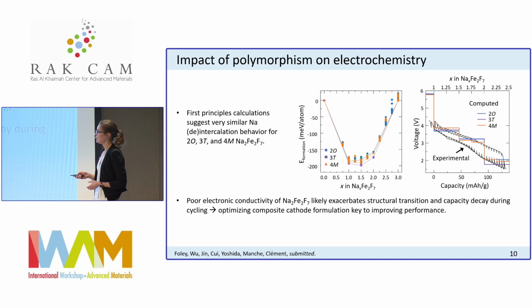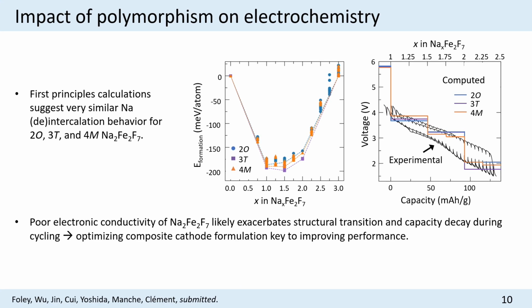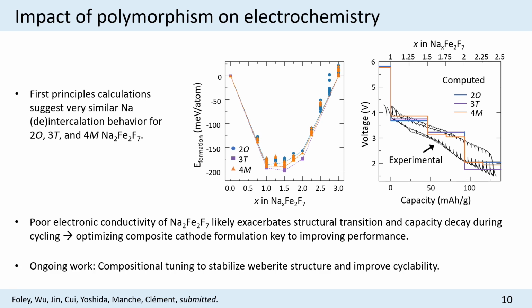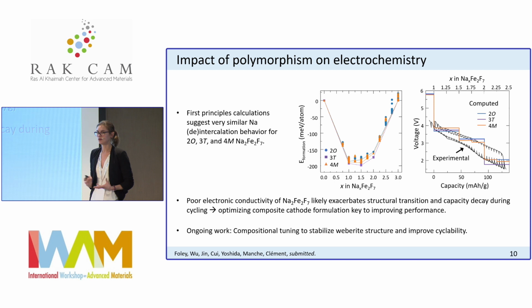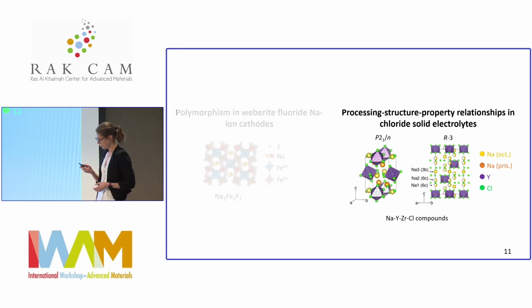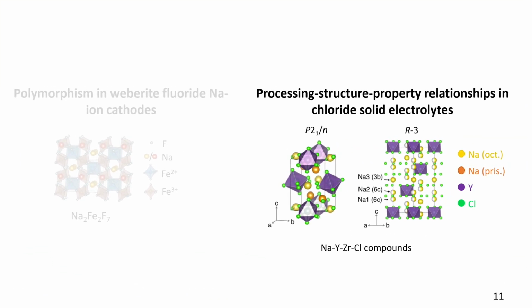We do believe, though, that the phase transformation that I discussed is not necessarily an intrinsic problem for this Weberite cathode. It's more the way we are processing the material into a cathode film. So right now we are trying to improve the way we formulate these cathode films to increase the electronic conductivity of our film, because we really think this is the main problem that's leading to this structural transition. We are also looking at tuning the composition further to stabilize the Weberite structure. So we're doing a screening of formation energies of various compositions for Weberites, and to improve the stability. The cyclability, sorry.